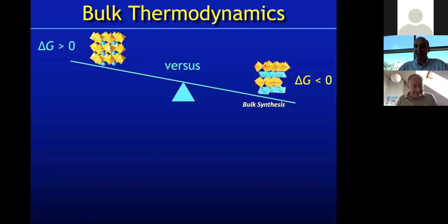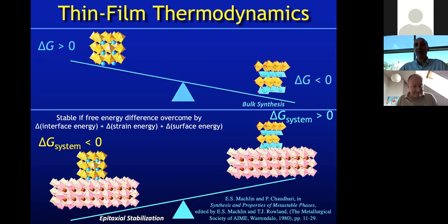Now that's a difficult thing to do in bulk, and it's always good to grow high quality materials quite slowly and have thermodynamics on your side. The trick that's used in thin films is not to defy thermodynamics, but to change the thermodynamic system from being just the bulk material to the combination of the substrate and the thin film of this material on top of it, okay? So by changing the system from just a beaker full of this or a beaker full of that, where the volume free energy of this wins, by changing the system to involve the substrate, and the key thing is the interface with this thin film, you get these additional free energy terms, okay? So if you choose